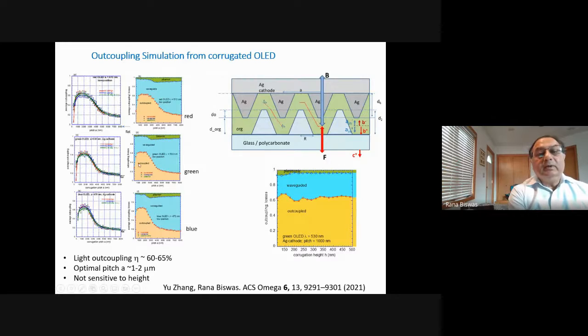And what you're seeing here is the result of simulations which were just published last year. And it shows you that the outcoupling of light can reach 60% for either red, green, or blue if you have an optimal pitch of about 1 to 2 microns. And the remainder of the light goes into these wave-guided modes or substrate modes, and a small amount of light is trapped in the plasmonic modes, less than 10%, much less than a flat structure.